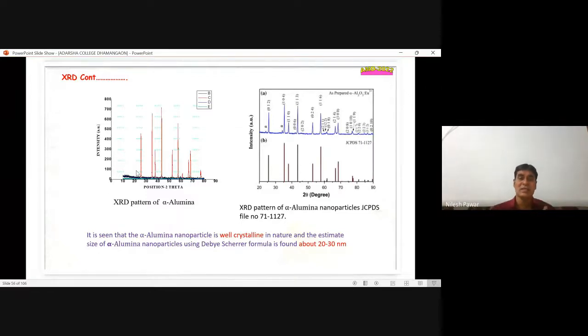When we synthesize any nanoparticle, then we conclude that the nanoparticle is perfect for further study, for characterization, for analysis, by comparing it with the standard data. It is seen that the alpha alumina nanoparticle is of well crystalline nature, and the estimated size of the alpha alumina nanoparticle by the Scherrer formula is found to be about 20 to 30 nanometer.